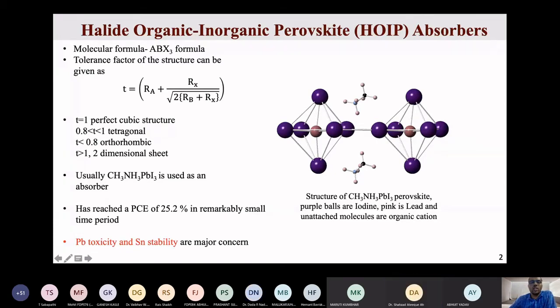So you talk about the ionic radius of the ABX3 formula. You have CH3NH3 as A, B as a lead or metal, and X is iodine, bromine, or chlorine. So you have this ABX3 formula of the perovskite, in which you can determine the tolerance factor T by knowing the ionic radius of the respective constituents, and that allows you to determine the value of T. If T is 1, it gives a perfect cubic structure. If T is between 0.8 and 1, then it gives tetragonal. If T is less than 0.8, then it becomes orthorhombic. And if T is more than 1, then these are kind of 2D perovskite sheet kind of